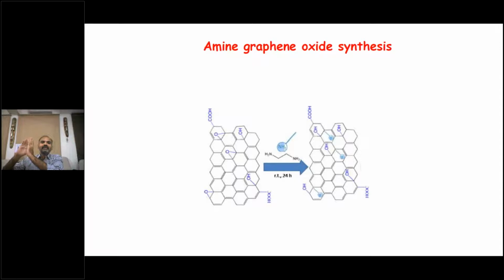Okay, so the graphene oxide is like this. The graphene oxide is activated in 2 steps to bind an acid-sensitive link, hydrazone. That hydrazone is conjugated to the preservative. When a fruit goes for over-ripening, post-ripening, there is a 3 times increase in the acidity of the fruit. There will be exudation of the acid from the fruit. That will start cleaving these hydrazone links that are sensitive to the acid, and then the preservative starts releasing, and the enzymatic reaction that is causing over-ripening will be quenched, and the preservation and the shelf life can be extended.